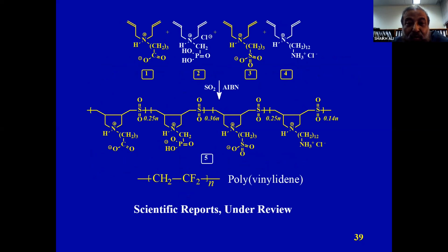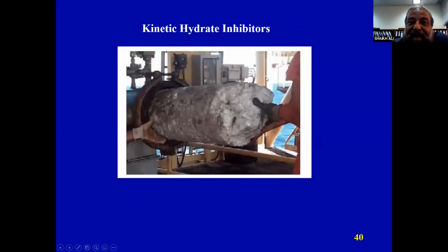And here we have taken this polymer 5 and we have blended it with polyvinylidene fluoride, and that has improved the permeation flux, and it has improved because it does not allow any precipitation of calcium sulfate on the membranes or others, because these groups can take care of them. And this is hydrophobic carbon 12 that makes this compatible with this polymer membrane. Now I'll take you to kinetic hydrate inhibitors.